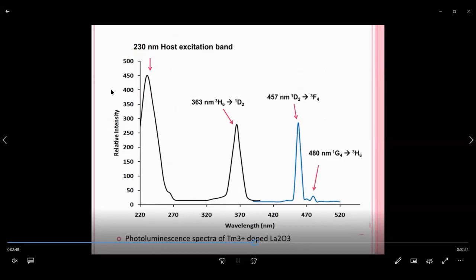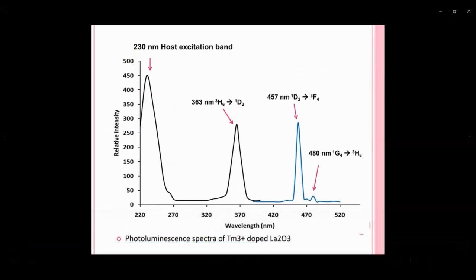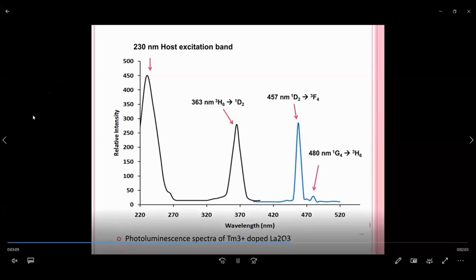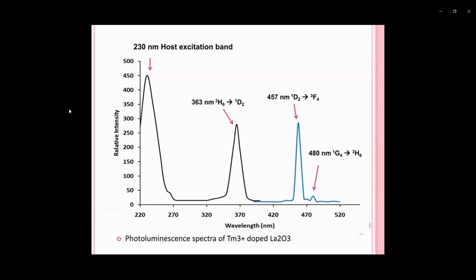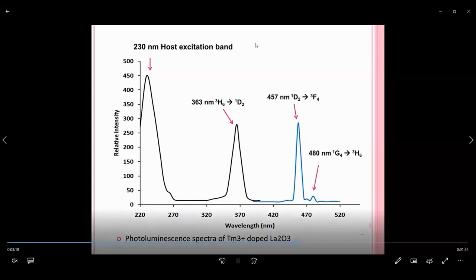This is the photoluminescence spectra of Tm3+ doped La2O3 phosphor. The black curve is the excitation spectra. It shows two excitation bands. The main excitation band peaking around 230 nanometer is due to the host excitation band, and another excitation peak is at 363 nanometer. It is attributed to the transition from 3H6 to 1D2 level of Tm3+ ion.